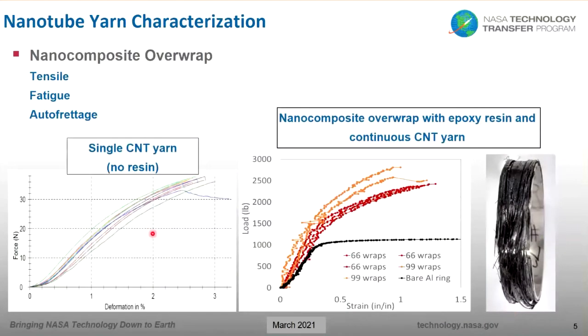In order to gather sufficient mechanical property information for our flight tests, we conducted an extensive amount of tests designed to understand how these nanocomposites would behave as an overwrap material under various conditions. Throughout all of those tests, we were able to get a really strong understanding of the material performance of these nanotubes going into the flight test. And although the nanocomposite overwrap was not as strong as the aerospace grade carbon fiber that we are accustomed to for this application, the properties of the nanotube yarn by itself were quite impressive.